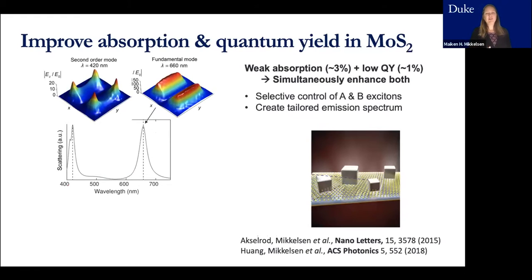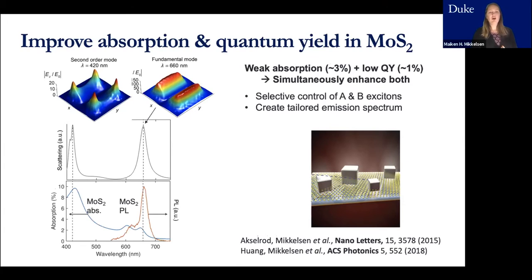Next, in all these experiments so far, we only used the fundamental resonance of the structure, but we also have a second order mode. So here is showing the fundamental mode, but we also have the second order mode that we typically haven't utilized. But it's actually very convenient to have two resonances to play with, in particular for two-dimensional materials. And we tested it out in monolayer MoS2. So here we have a weak absorption and a low quantum yield. So we set out to see if we can simultaneously enhance both using these two resonances. And it so happens that the fundamental resonance is overlapping with the emission here, so we can enhance the quantum efficiency as well as the spontaneous emission rate.